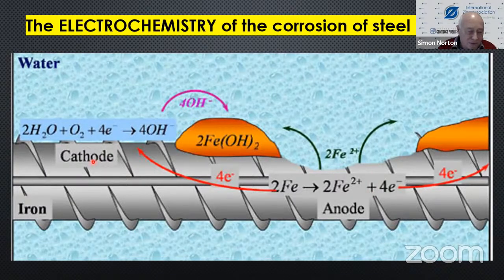And on the surface of steel, there are thousands of anodes and cathodes, and they're all reacting simultaneously. At the anode, you have what's called oxidation. You lose electrons. And at the cathode, you have what's called reduction. So here we've got oxygen being reduced to the hydroxide ion. That reacts with the ions in solution, and you get iron hydroxide, iron oxide, and you get corrosion. And slowly, your steel or your material is taken and disappears. That's where zinc comes in. Zinc coated on the surface protects it.